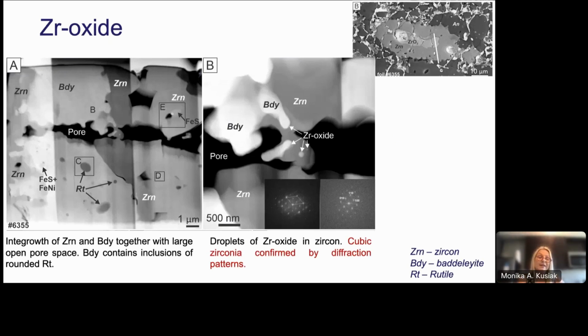And zirconium oxide, which probably is one of the most interesting discoveries found during the analysis of these grains. In these samples we have not only monoclinic baddeleyite; at the beginning, whenever we saw zirconium oxide, we called it baddeleyite, but then we found out that we have cubic zirconium oxide. So baddeleyite is monoclinic, then tetragonal zirconium oxide, and then cubic zirconium oxide. So three forms of zirconium oxide occur in these samples.